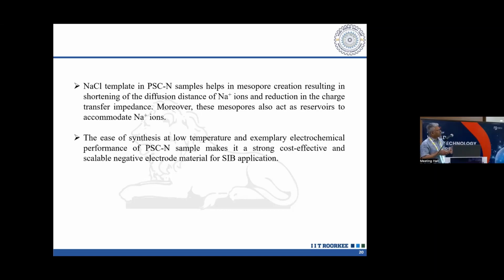And reduction of the charge transfer impedance. Charge transfer resistance has to be as minimum as possible. Then what will happen between electrode and electrolyte? If the charge transfer resistance is very high, then it will lose a lot of energy while crossing it. So that should be minimum. So this is the study, and we have been successful to some extent. Moreover, the mesoporous structure acts as a reservoir. Because the pore volume is more, more and more sodium, the active ion, can be contained.